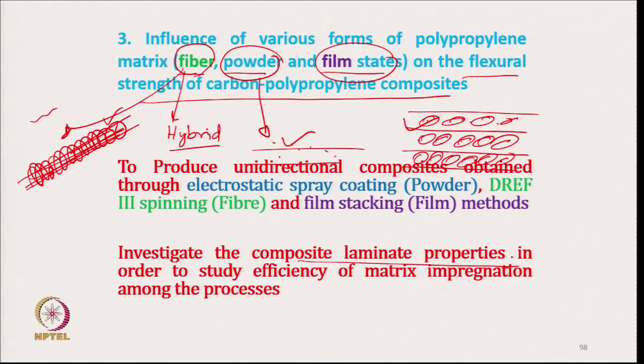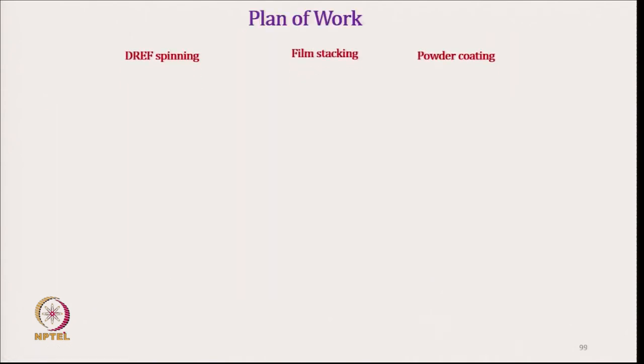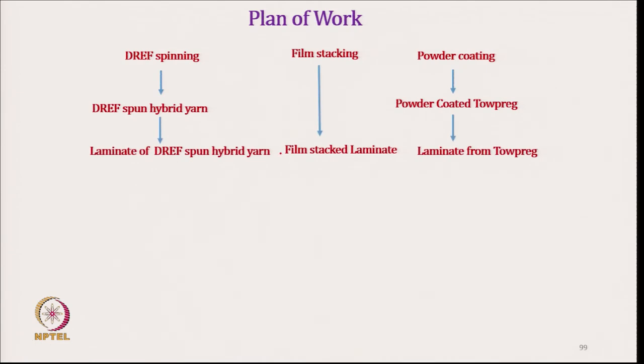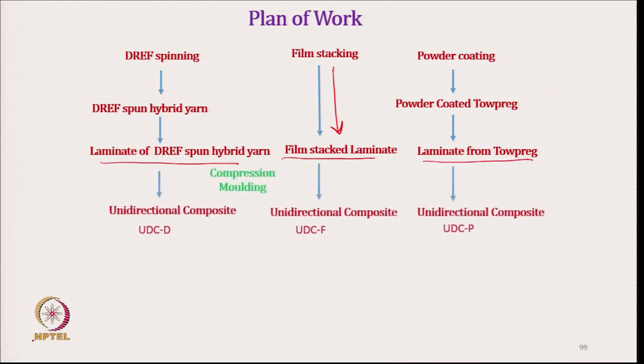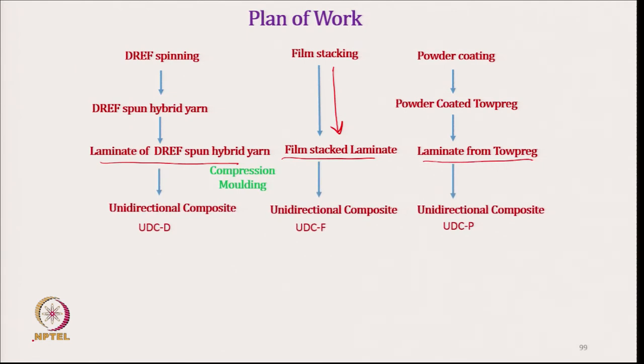Composite laminate process. So, we will make the composite laminate. The total plan of work is that first DREF spinning we will be doing using polypropylene as a fiber, then film stacking and powder coating. The DREF spun hybrid yarn, powder coated Towpreg, then film stacking will be done directly on the carbon tow, then we will form the laminate, okay, laminates of DREF spun yarn, film stacked laminate and lamination from the powder coated Towpreg. Then compression molding will be done to form the composite.